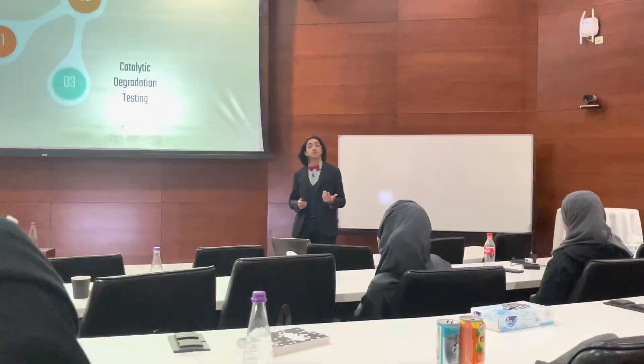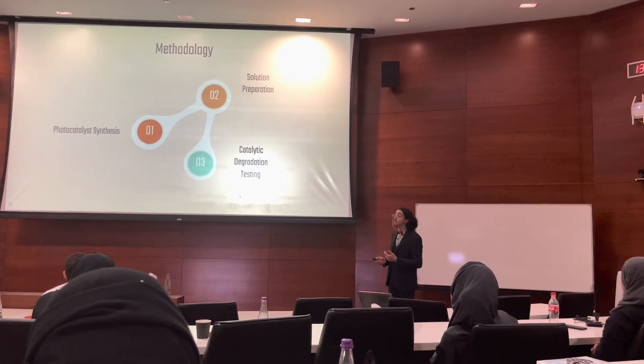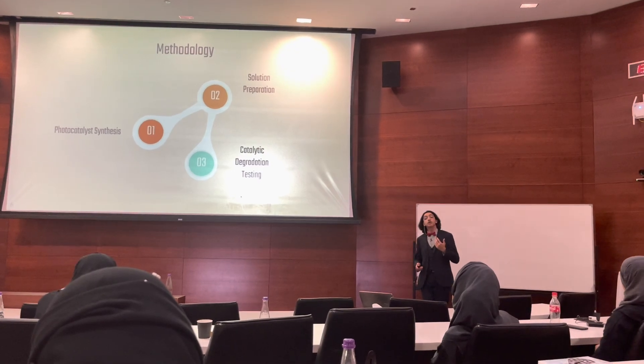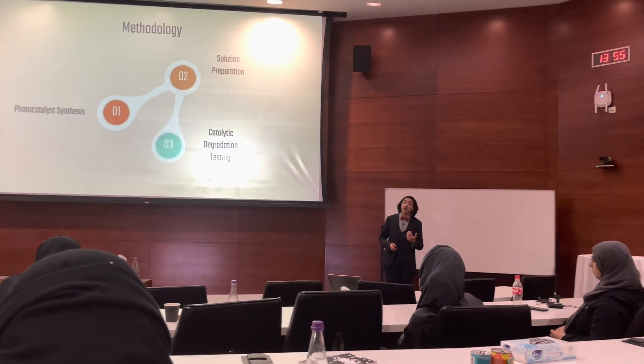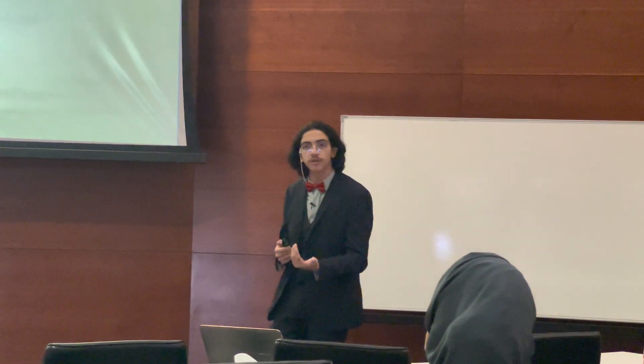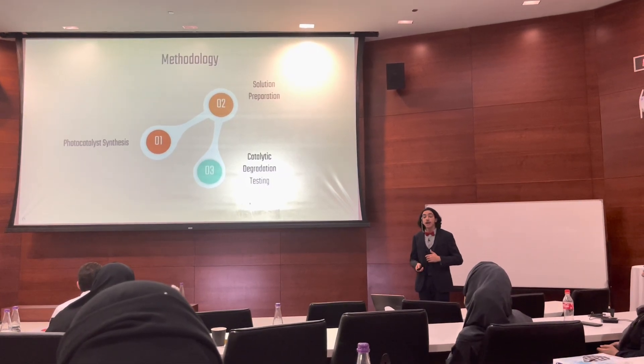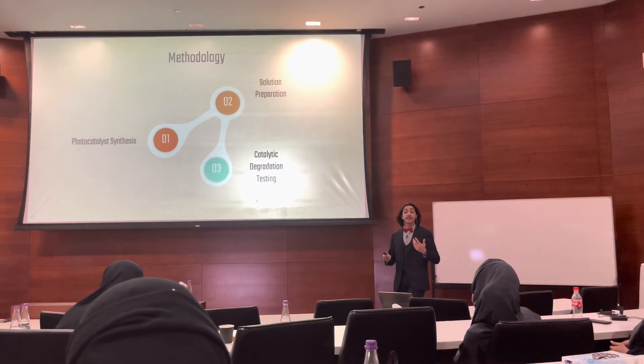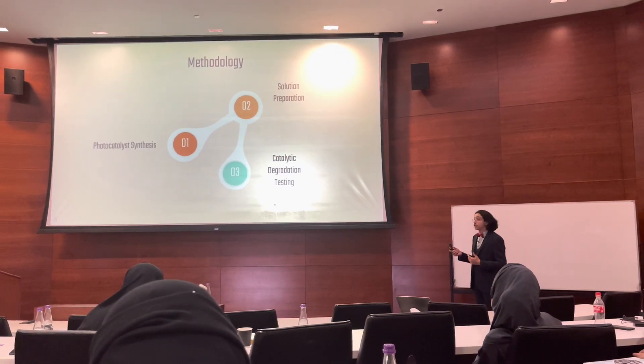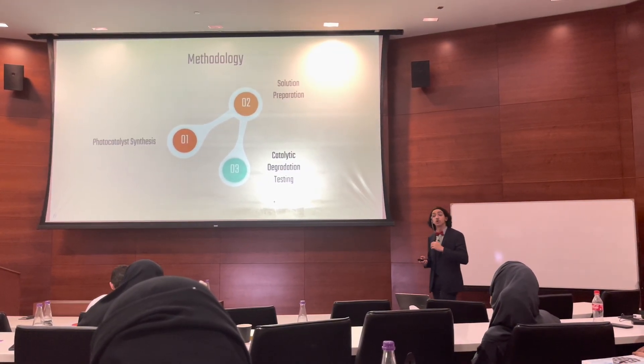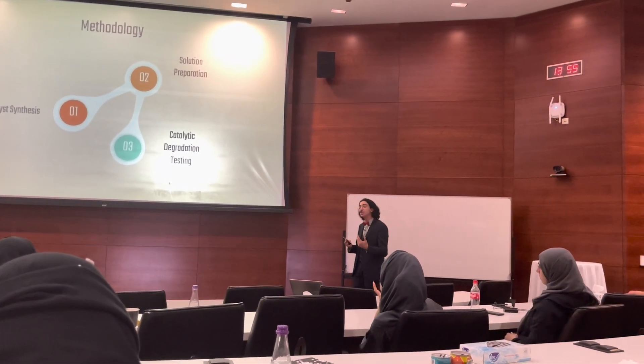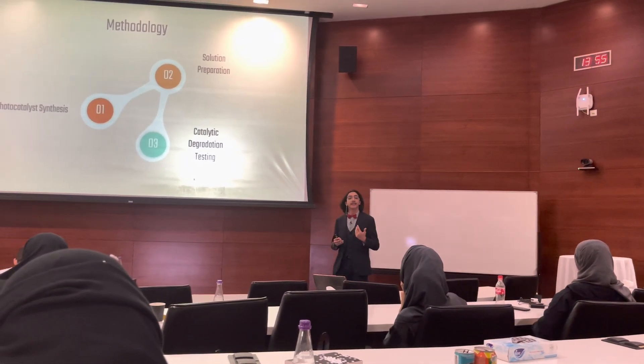For this project, I used zinc oxide tetrapods, which are a very unique geometric structure. After obtaining these photocatalysts, I prepared several solutions of organic dyes — specifically methylene blue, one of the most prevalent and dangerous dyes in the context of water sanitation and purification. I prepared solutions of different concentrations to replicate the wastewater I'm attempting to purify, then added controlled quantities of catalyst in predetermined ratios to compare how well my catalyst degrades these organic molecules.